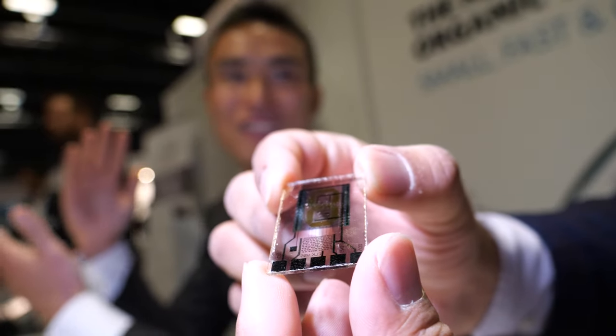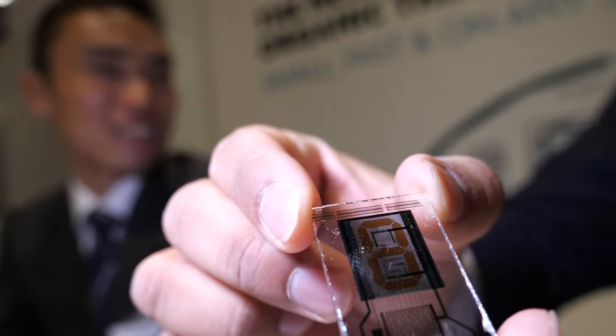What have been the benefits of this material versus previous generations? This is a new organic semiconductor material. It's really air stable, and the thermal budget for processing is really high. It's also stable after photolithography. Many demonstrators are produced by printing, but we use photolithography because it's more compatible with current industry systems. The channel length of the transistor is just five microns — ten times smaller than other printed TFTs — so we can get much better TFT performance.